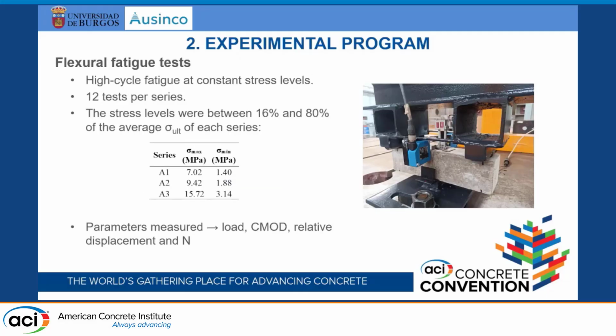And finally, we have made the main tests, which are the flexural fatigue tests. Here you have an example of this. These tests are made on notched specimens, also uncracked. So here you see an example. We are a bit strange in Burgos. We do the flexural fatigue test upside down, here with the two supports over here. The notch is around here, and here is the main support, right?